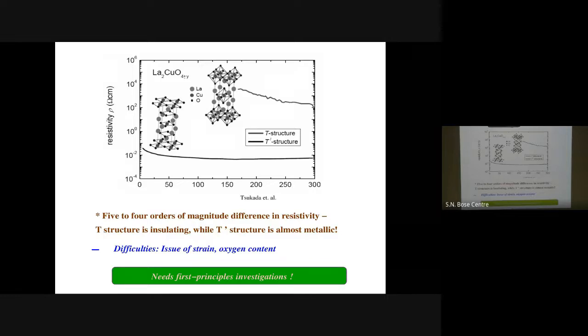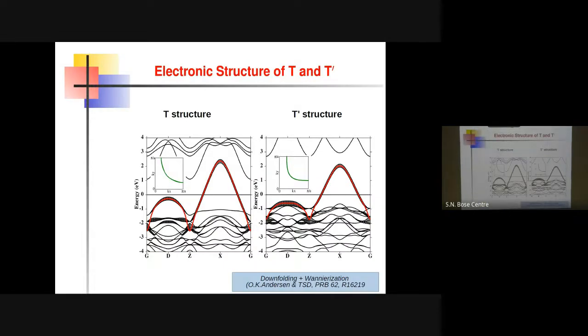Well, this paper created a certain sensation, but then people criticized because all the samples were in film form. So there were issues of strain and oxygen content. So we thought of investigating it with our calculation. This is the band structure of the T structure lanthanum cuprate and T prime structure lanthanum cuprate. The zero of the energy is set at the Fermi level. Very simple band structure. Only a single band is crossing the Fermi level. And this single band, if you are not an expert, looks pretty similar between the two. You can actually calculate the Fermi surface of this single band. You can see that the shape of the Fermi surface is quite different. For the T prime structure, it's more rounded, while for the T structure, it's a bit squarish.